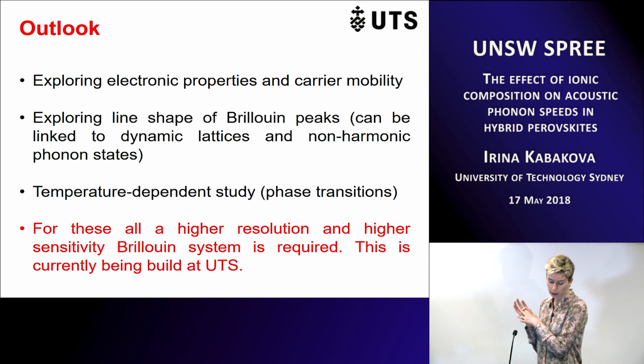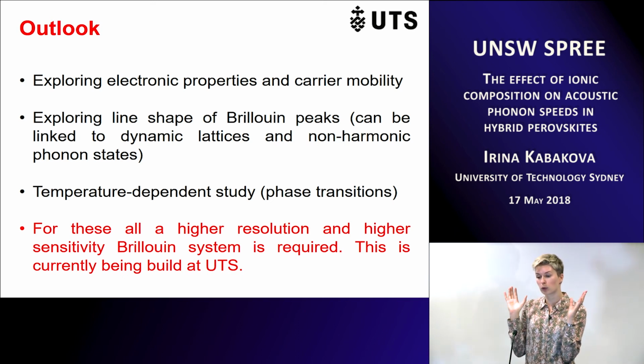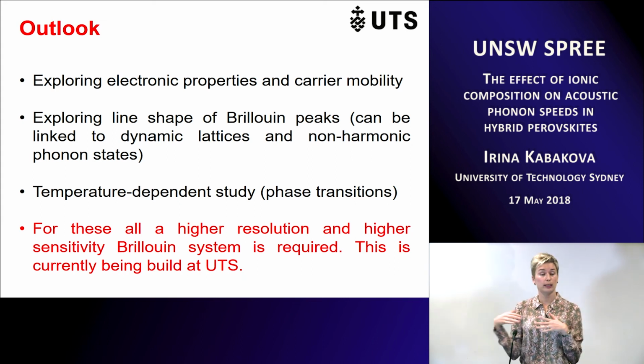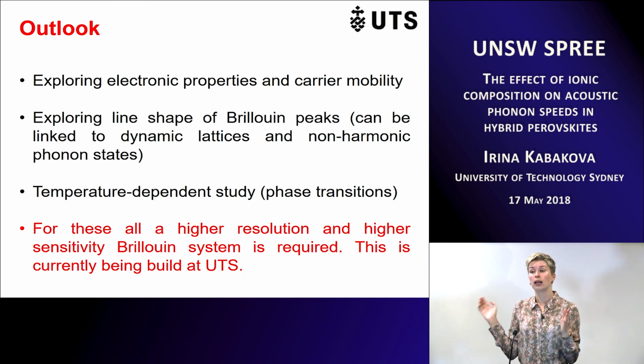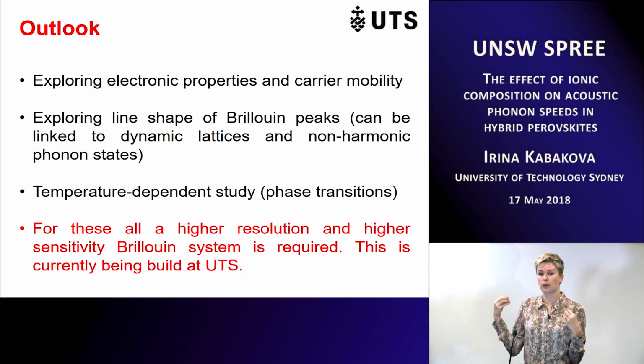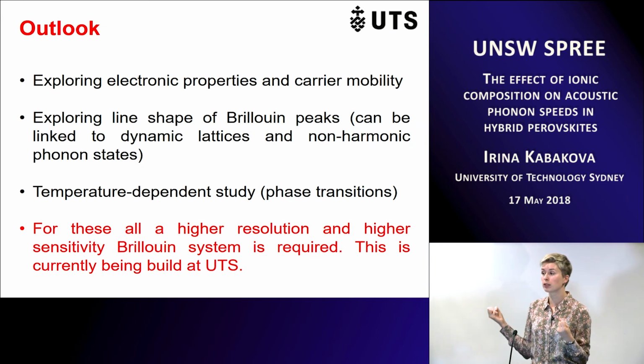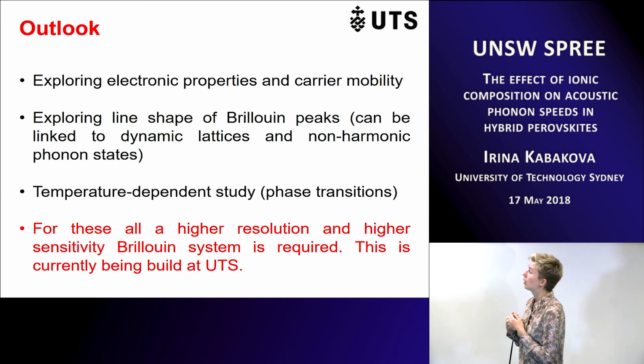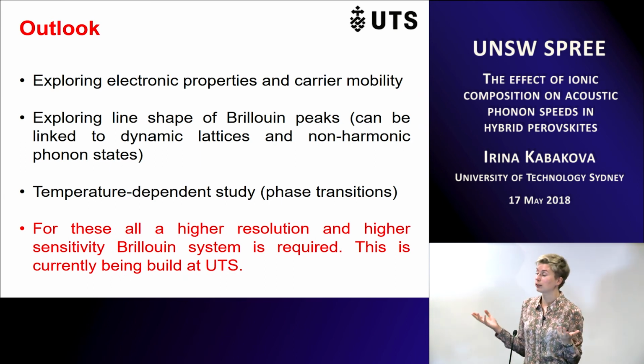As well, a very important issue is exploring the line widths, because so far we only calculated where the peaks are located, but we didn't study the line widths, because we didn't have enough resolution in our spectroscopy system to resolve them properly. What we did was just fit with a Lorentzian curve, assuming a harmonic oscillator model, but that's actually very far from the truth, and there are many reports of anharmonicity of these lattice vibrations, and that the peaks are not Lorentzian.